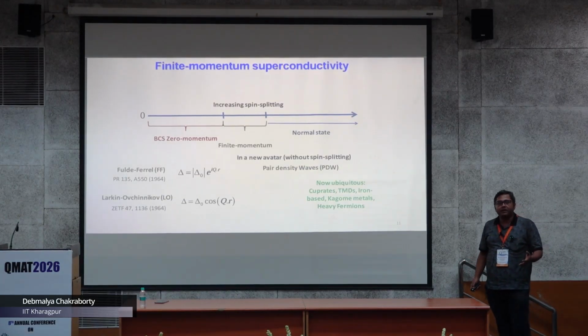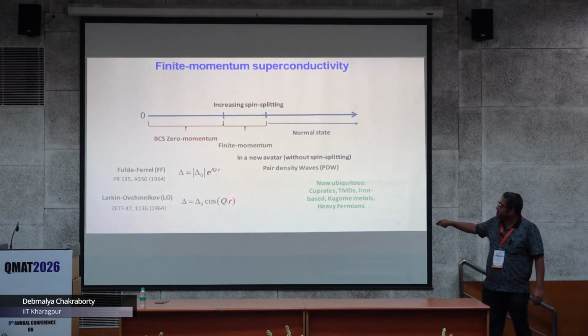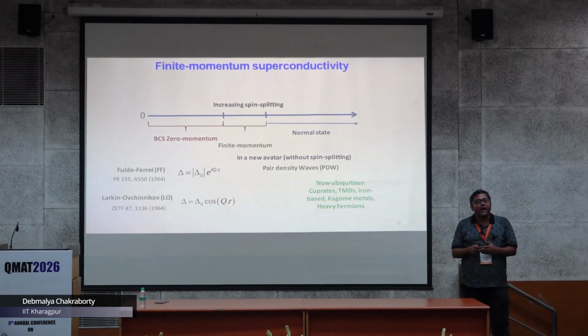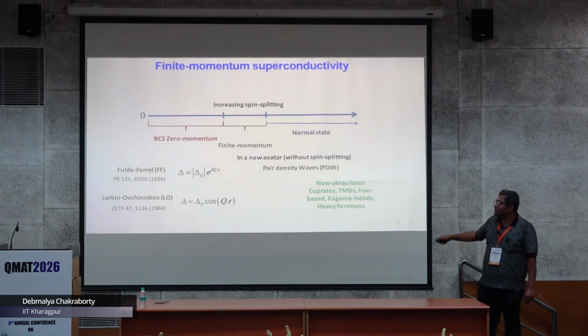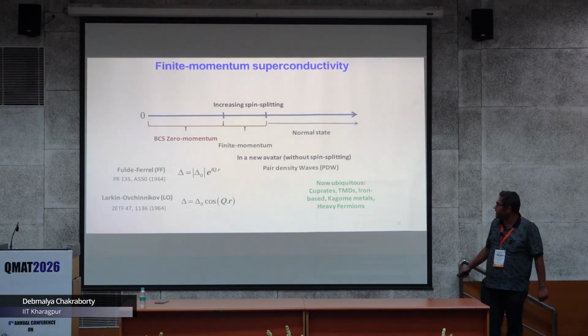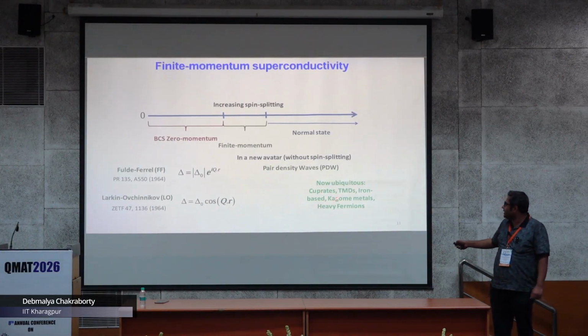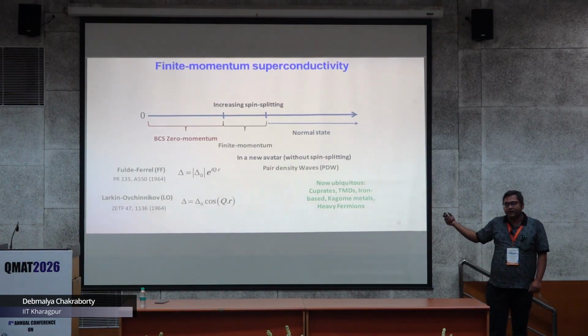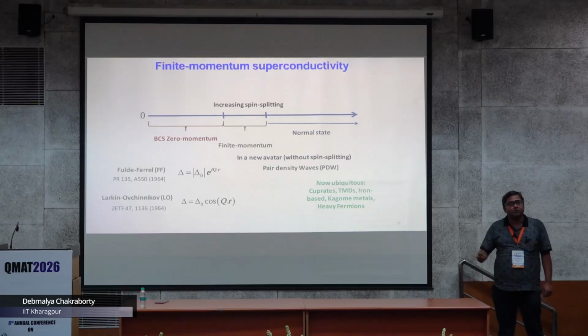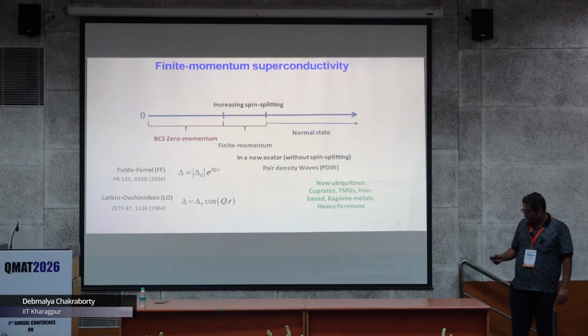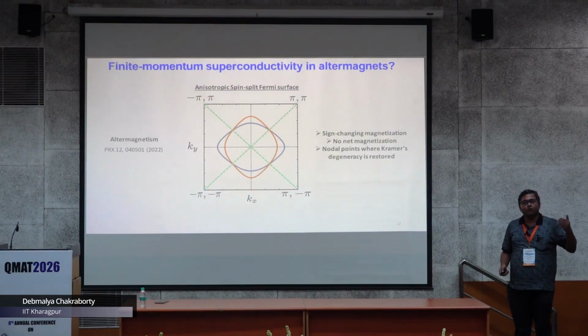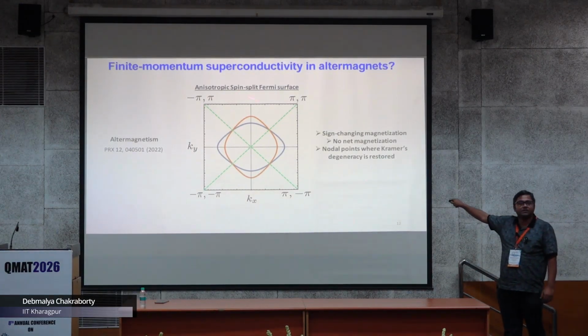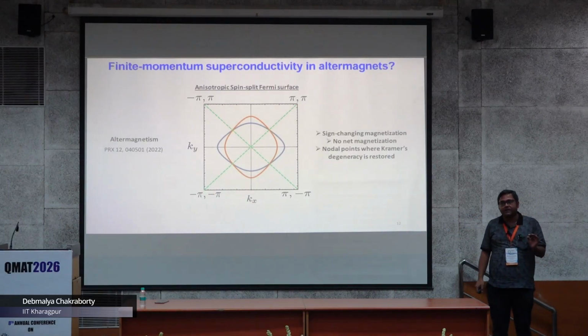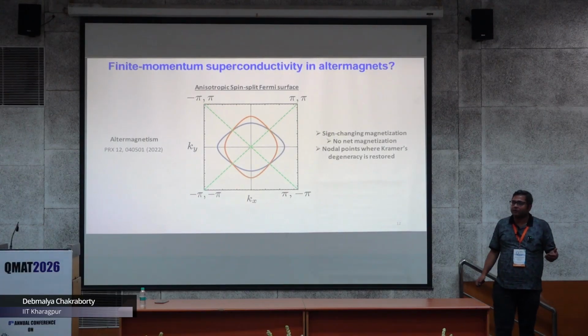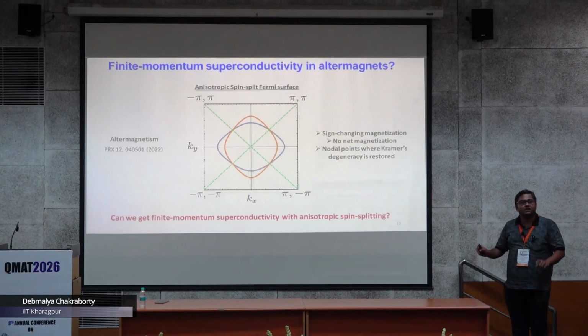More recently, about 8 years ago, they came in a new avatar called a pair density wave, where we do not have any spin splitting, but they still show some modulating superconductivity. They are seen in many compounds now: cuprates, TMDs, Kagome metals, iron-based superconductors, and many others, actually in heavy fermions. So with this new avatar, we can ask the question within the altermagnet, which has this structure. Let's say we consider the d-wave altermagnet, which has sign-changing magnetization and nodal points. Can we get finite momentum superconductivity with this structure? That was our original question.